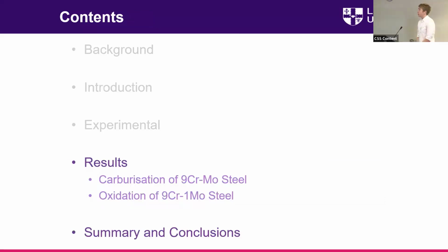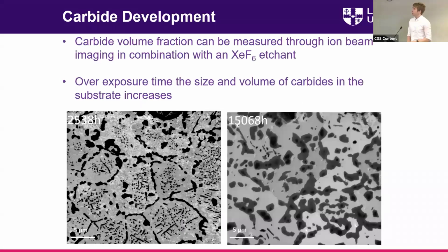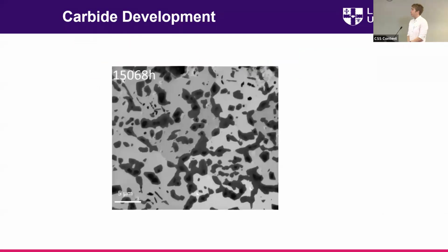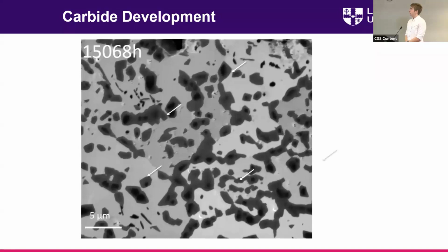So now I'm going to just move on and talk about the carburization. So the carbide volume can be measured using ion beam imaging in combination with xenon hexafluoride etchant. So just a quick visual comparison there. On the left, I think it's about 2,500 hours, and on the right is about 15,000. So you can see that the carbides within the substrate are increasing in size and decreasing in frequency as they effectively coalesce together. But if we take a look at the 15,000 hour sample, we can see slightly different contrasts within these ion beam images, which suggests that they're increasing in complexity as well towards the later stages of oxidation.